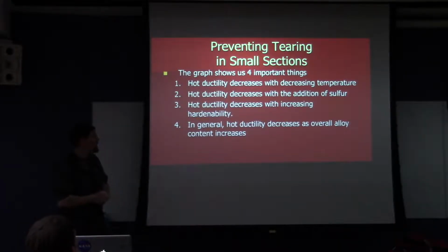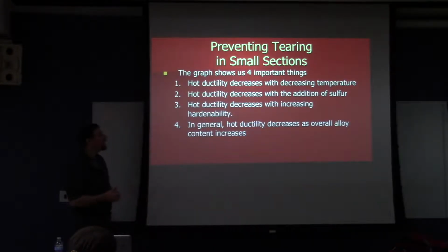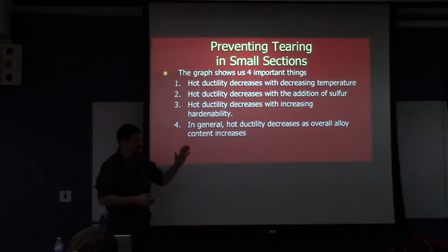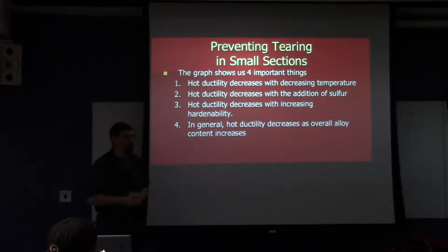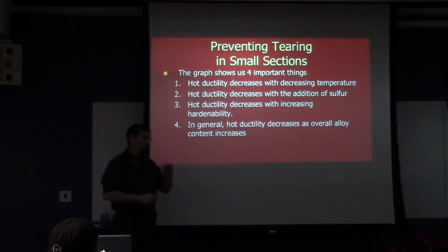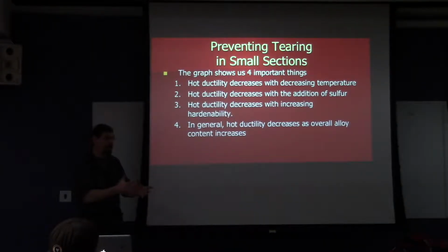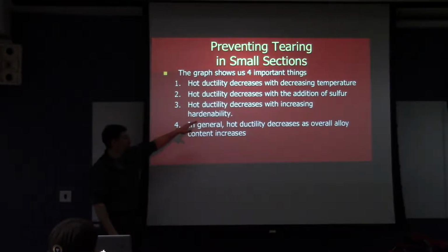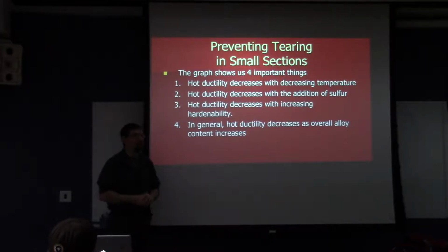So summarizing that graph, we see that the hot ductility decreases as temperature goes down. It gets harder to move metal as it gets colder. Hot ductility also decreases when we put sulfur in steel. And then, of course, we put sulfur in really primarily to aid in machining. You'll see, and we may talk about it in a later lesson, we will put very small amounts of sulfur in many of our grades, not for machinability, but to help with a different problem. But that addition is very low, and that small amount of sulfur really doesn't cause this problem. It's when you get to a high level of sulfur where you have a lot of manganese sulfides that are formed that you have problems with hot ductility. We also can see that hot ductility decreases with increasing hardenability. Another way of saying that is, as the alloy content goes up, the hot ductility goes down.